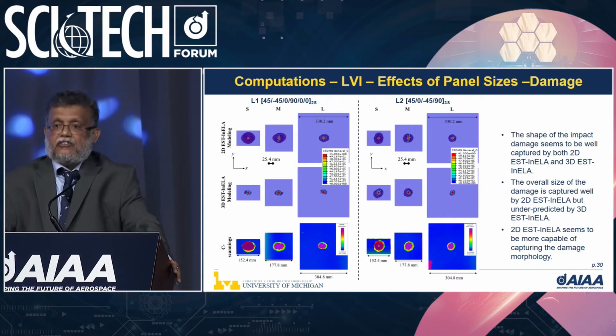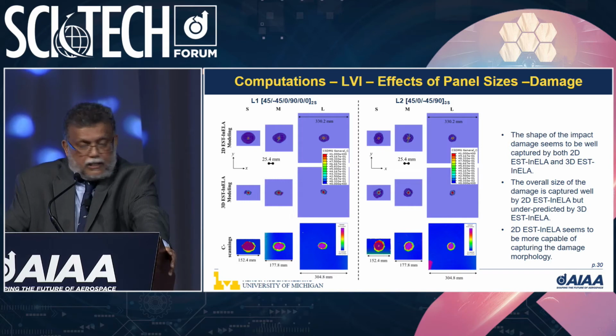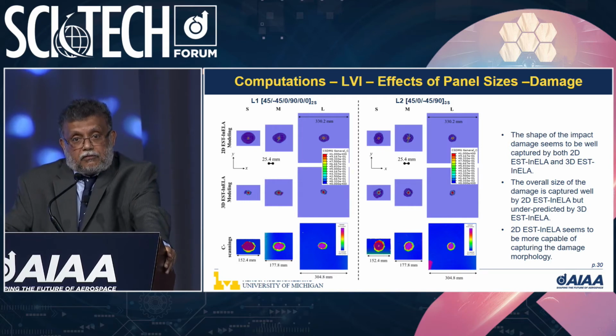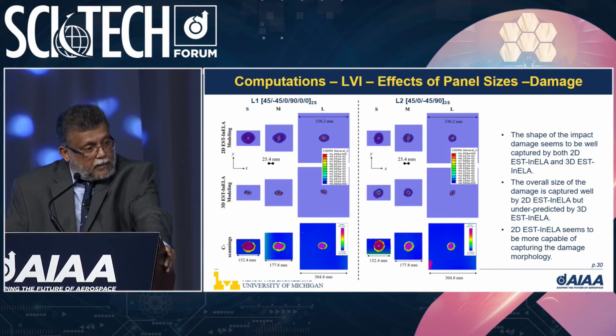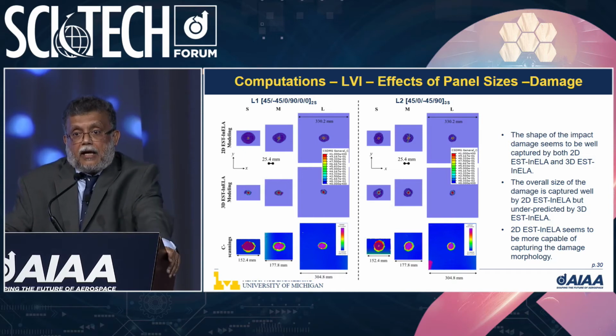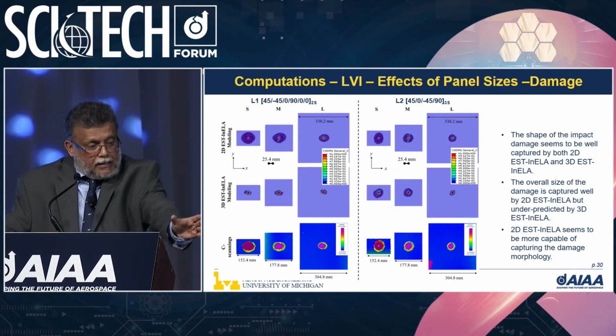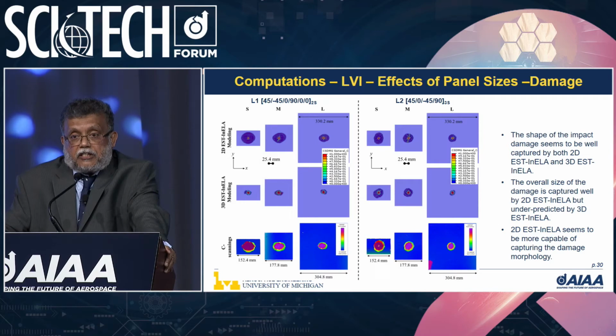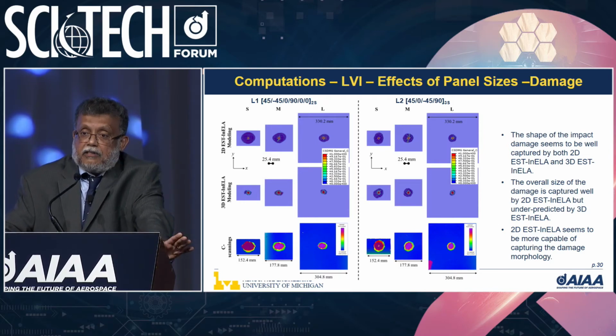Now, it also is able to capture the damage footprint for different layups, which is another test for a code. Can you do this when you change the layup in a laminate? And here you can see that both the experimental results and the EST predictions are well within the levels of accuracy that one would want for a predictive tool.